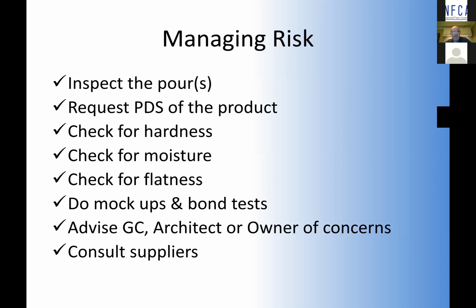So just to recap, whether you're the flooring contractor or a manufacturer of materials, we all have risk in this and we all have skin in the game. So if I can put a checklist together: inspect the pour, even if it's a cement-based material, check to make sure that it is what it's supposed to be. Get a copy of the PDS of the product, because there should be a design mix, or a recommendation or a specification in place for what was supposed to be there. Check it for hardness, check it for moisture, for flatness. Do your bond tests and mock-ups in advance. And if you have any concern, then start to raise some white flags.